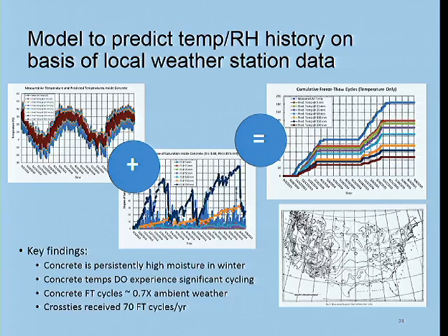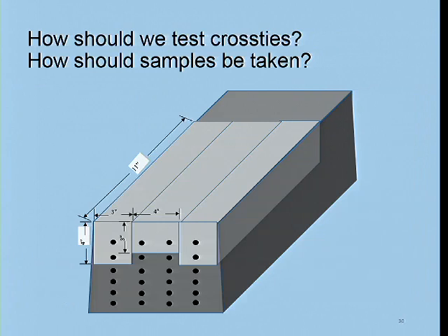So this tells us that we receive maybe, let's just guess, 70 freeze-thaw cycles a year. And you might recall that the C666 test requires 300 cycles for its torture test. So actually, within a few years, you've achieved those kinds of numbers of cycles. And therefore, you might feel that that is, in fact, an appropriate kind of testing to assess this material.